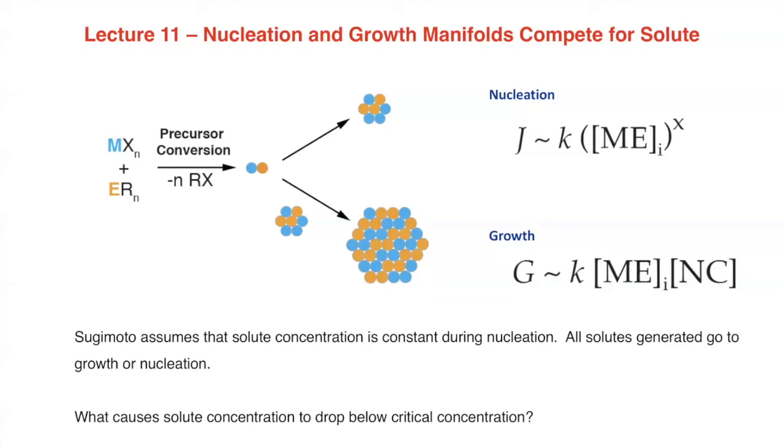The faster the growth kinetics, the sooner the nucleation turns off, because growth is the thing that turns the concentration downward and below the critical concentration. Okay, so if a given crystal is really good at growth, if it's a fast growing crystal, then it'll shut off the nucleation process faster, because it takes fewer crystals to turn the concentration downward to outcompete the solute formation and outcompete the nucleation process.